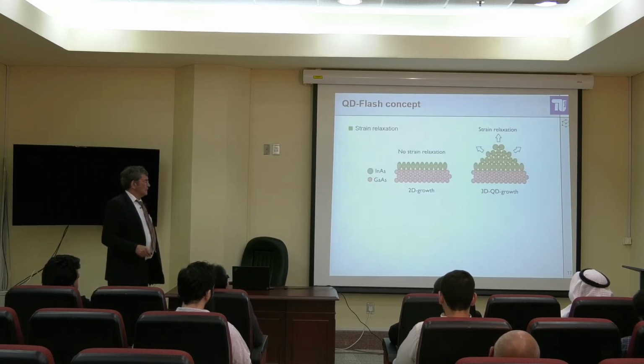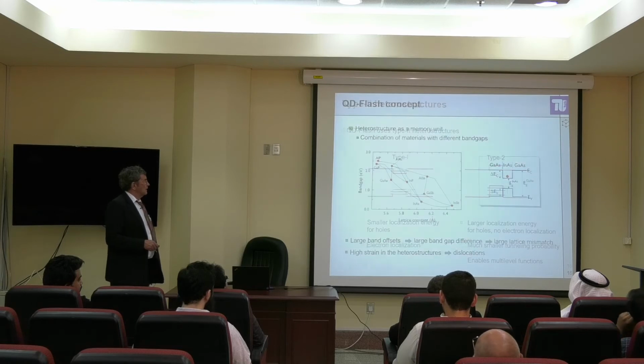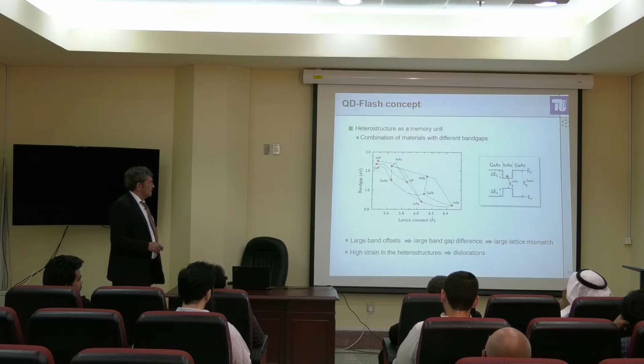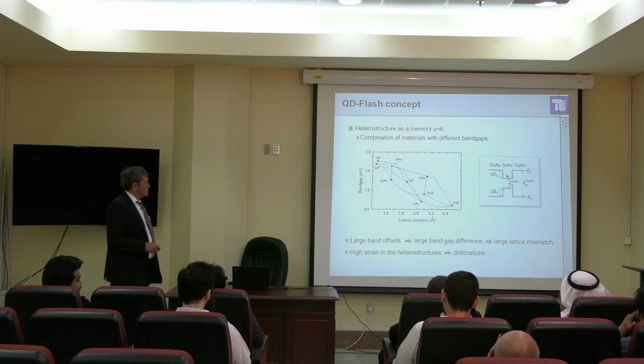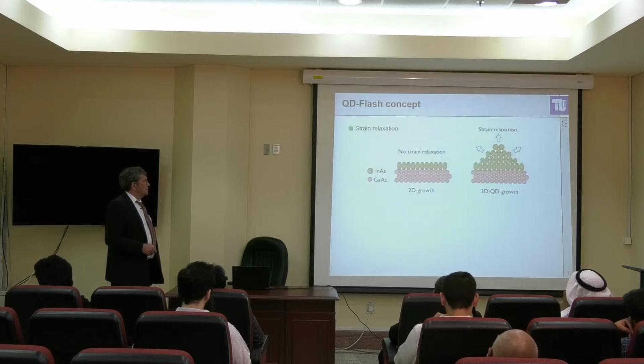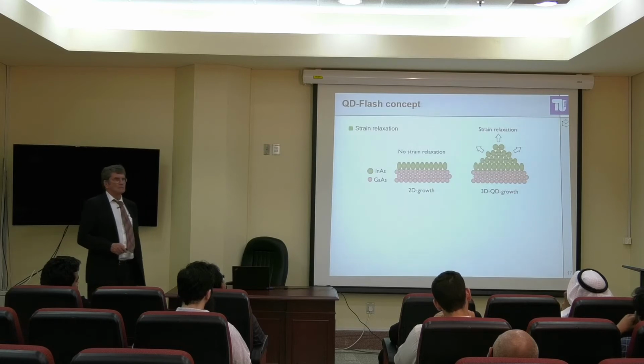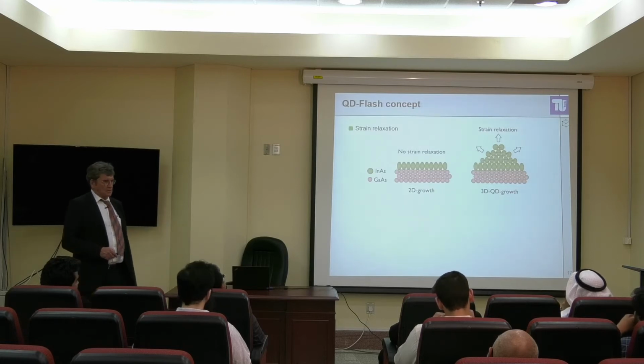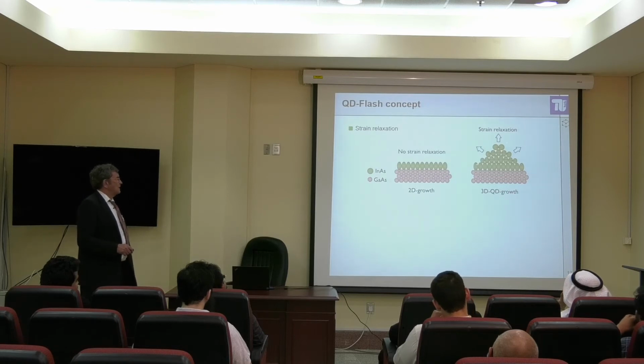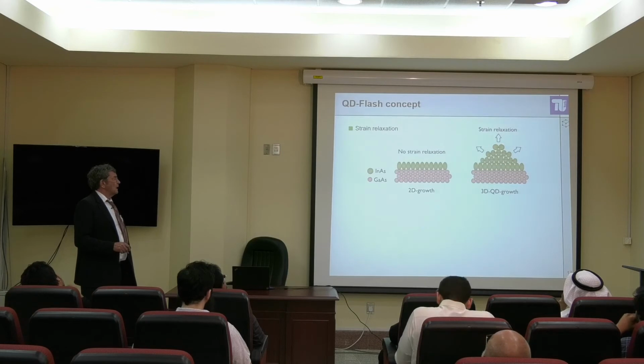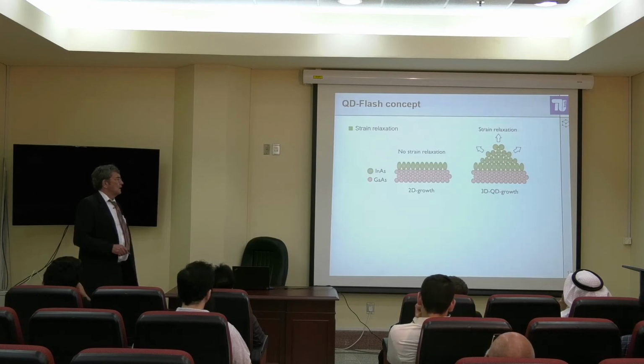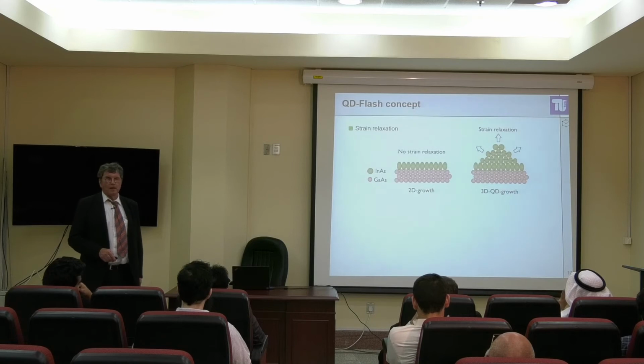So, the quantum dot concept is the following: you deposit one type of material which has a different lattice constant, like indium arsenide. You see here, close to 6.1 on gallium arsenide, 5.7. You deposit it, and then after one or two monolayers, you get strain relaxation. That means you get a decomposition of the deposited layer, and you get self-ordered three-dimensional quantum dot growth. And behind that is a first-order phase transition.